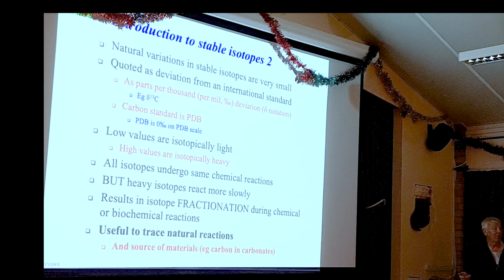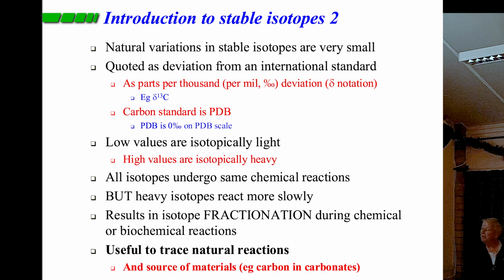Obviously there's no sample left anymore, but we have secondary standards which we calibrate to PDB, and now all quoted carbon isotope values will be relative to PDB. And the variations in the ratio are only parts per thousand. So what we do is we compare with the standard, and our sample might be isotopically heavier, i.e. more carbon-13, or isotopically lighter, less carbon-13. And then to make it sensible numbers, we multiply the difference by 1,000. So we finish up with a PDB scale, which is relating to the belemnite.